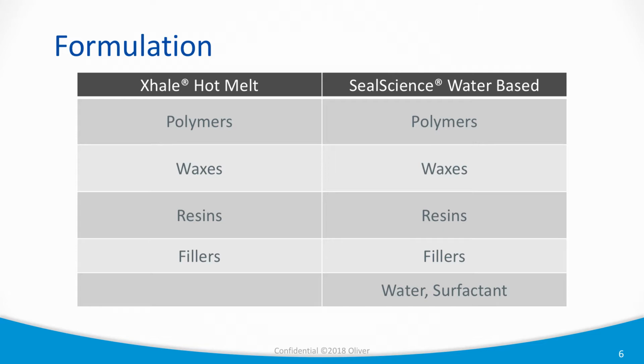And then we have resins. These are what people call hydrocarbon resins or tackifier resins, and these are to give specific adhesion to both the substrate, or to the coating substrate and the substrate that you're sealing to. And the optimum resin system is going to be different for different substrate systems. In some cases we use fillers. They're somewhat similar to waxes, can control the cohesive strength.